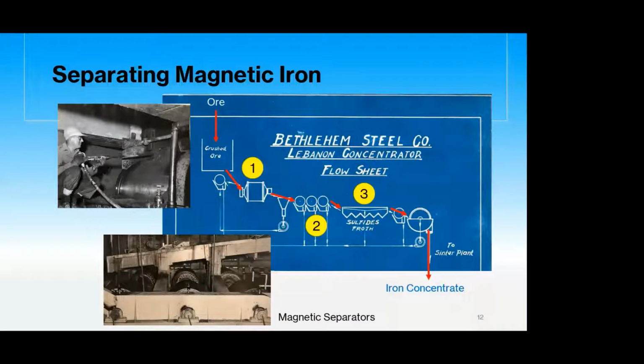The ground or milled ore was then mixed with water and fed into a series of magnetic separators, step number 2. You see those magnetic separators in the picture on the bottom of the slide. In this step, the iron mineral magnetite was attracted to powerful magnets, while the rest of the solution containing the remnants of the ore flowed downstream. Blades close to the rotating drums then scraped the magnetite off the drums to concentrate the iron.